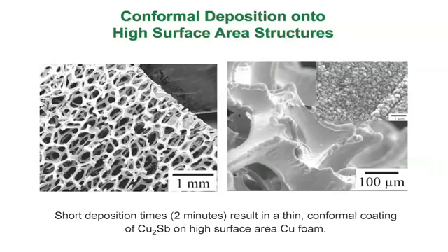A lot of the stuff we make is smaller than the wavelength of visible light, so we use a lot of electron microscopes. This is a scanning electron microscope image. This is 1 millimeter here. So, low magnification image, and you can see all these big holes. If you zoom in, you can see that everywhere there was an edge, the copper antimonide plated faster. And that's really normal for electroplating. And then the flatter parts, if you zoom in even further, you see these tiny little cubes everywhere.